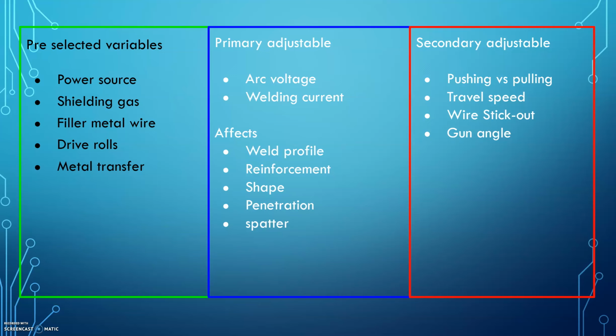If your stick out is too close, you can snag your nozzle in the weld or vaporize the deoxidizers in the wire and get worm tracks. If your stick out is too great, you decrease amperage and lose gas coverage. If there's slag, you drag, also known as the backhand technique, and welding too fast has its own issues as well.